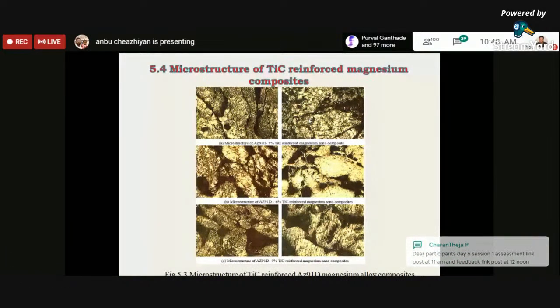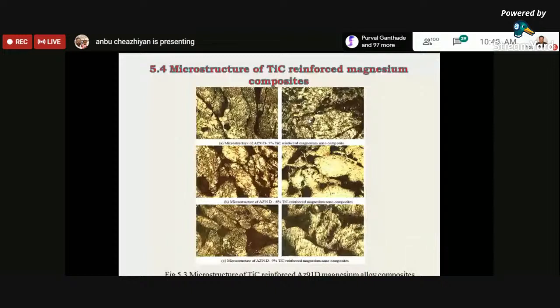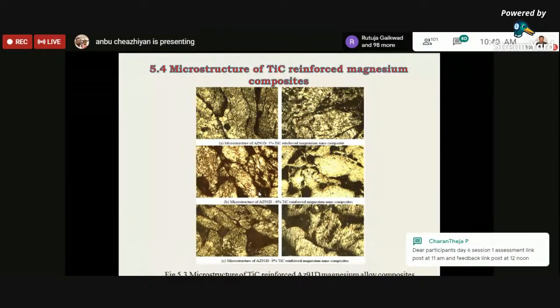So in the magnesium powder, it has been observed that the reinforcement particles are uniformly distributed without indication of clusters. But here we can see that some clusters are still found with the increase of reinforcement to 6%. Here we can see some particles of titanium carbide, so it shows that it is not diffused into the material. It appears as a fine powder in the composite materials.